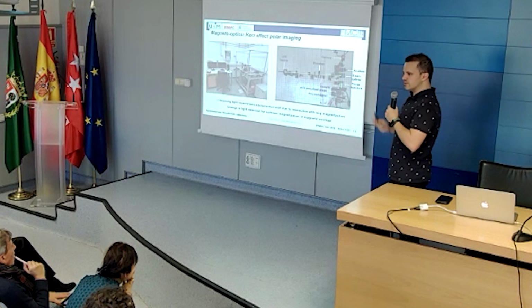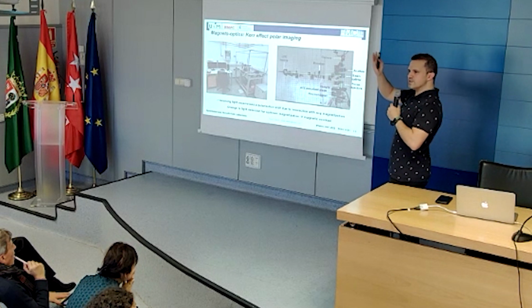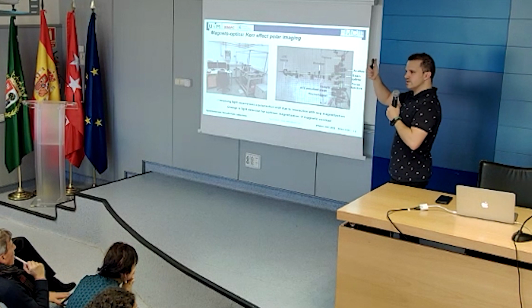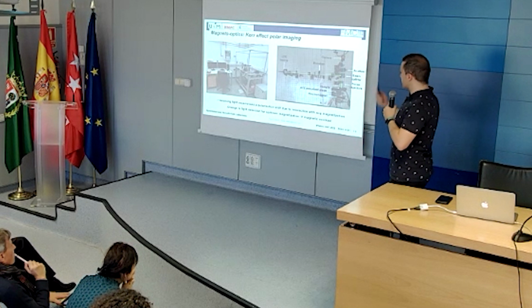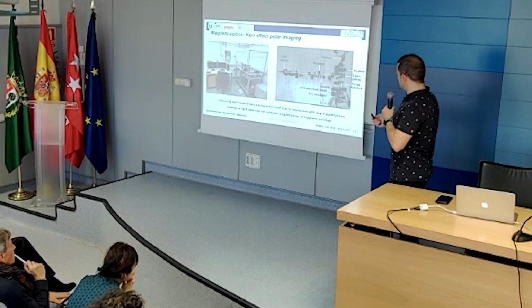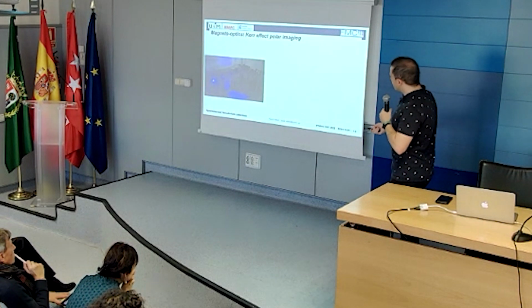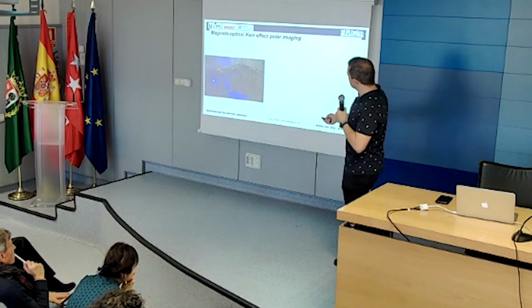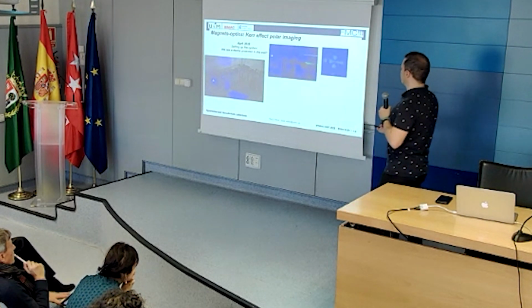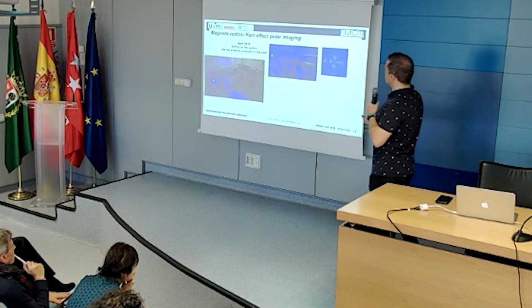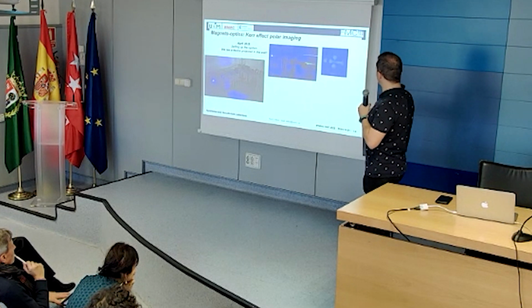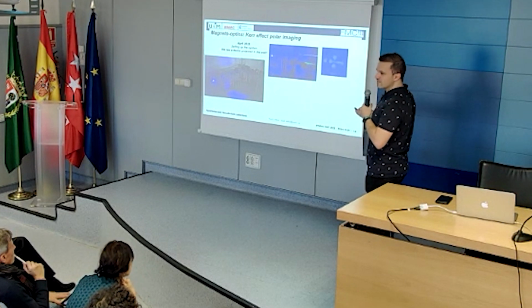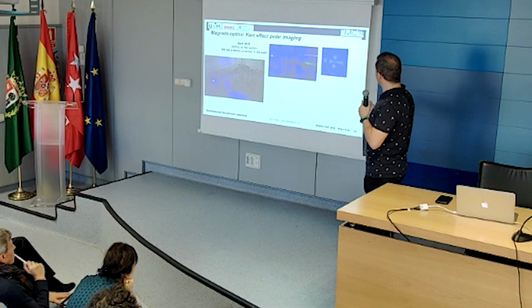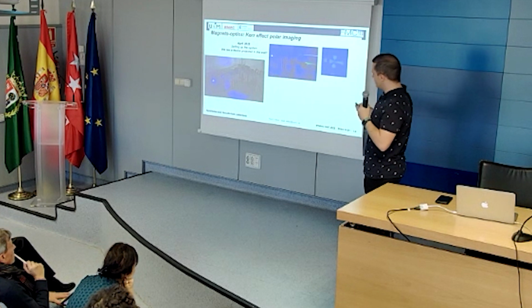That's what we are trying to do: measure these tiny changes when we are reversing the magnetization in the sample that is out-of-plane magnetized. When a certain domain is reversing, we have a change in the intensity. Now that's how the device looks when you shine light. This is still in optimization, but that was the very first image. It was not on the computer, it was on the wall when we did not have the camera set there, and we could already see the device was there.